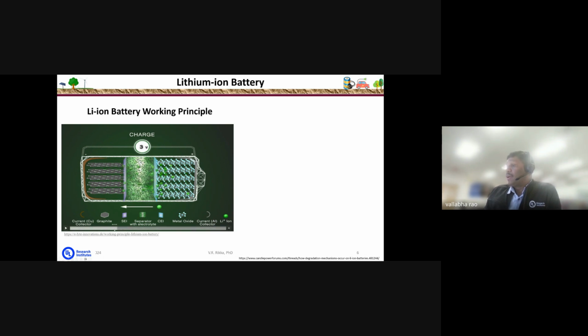If you observe clearly here, before using the lithium ion cell, or before integrating the lithium ions into the anode, we can see two interface layers formed, which are also known as solid electrolyte interface or electrode electrolyte interface layers. These are not designed before fabricating the lithium ion cell. These layers form during the electrochemical cycles. These layers are very sensitive and delicate, and they determine the rate performance and the safety of the lithium-ion cell at different operating conditions, which we will discuss in our further slides.